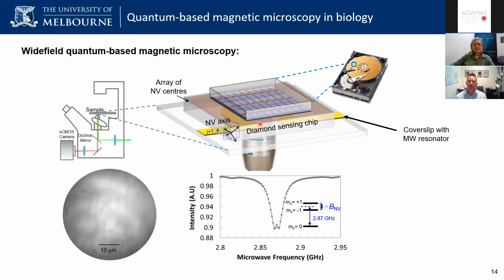I think it depends on the application. For ODMR, a lot of the time the sample will be large enough that you can afford it, and the fall-off is consistent with 1/R. That means that you're not losing a lot of the signal over the depth of the implant. So if you're doing ODMR imaging, you can afford to be a little bit deeper.